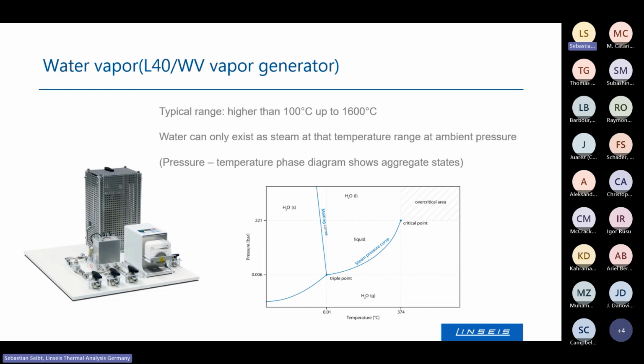As I mentioned at the very beginning, in contrast to humidity, we also have vapor generators for water vapor experiments. Because if you exceed 100 centigrade at ambient pressure, or if you exceed the boiling temperature of water - because at higher pressures it may be a little bit higher than 100 centigrade - you're in a range where there is no longer humidity. You cannot speak about relative humidity in a range where water is gaseous.